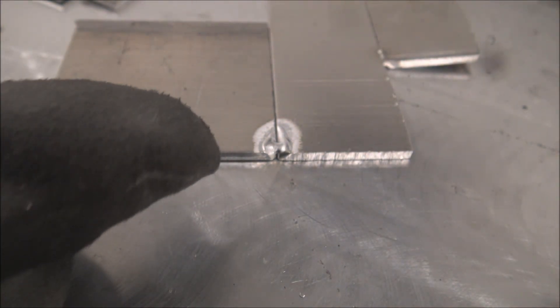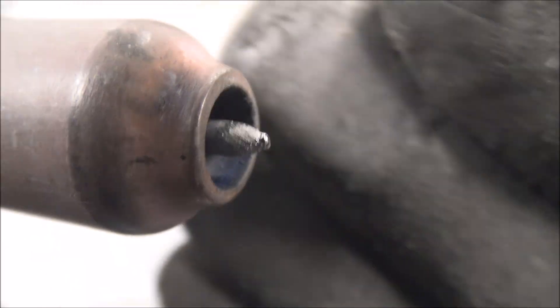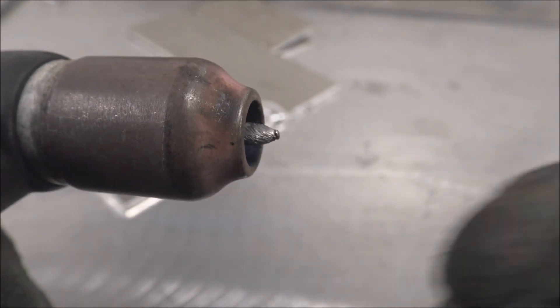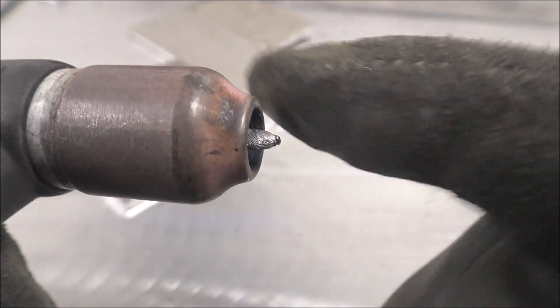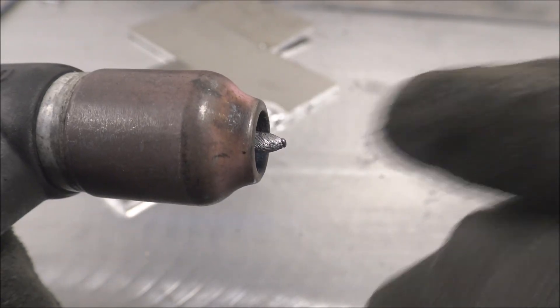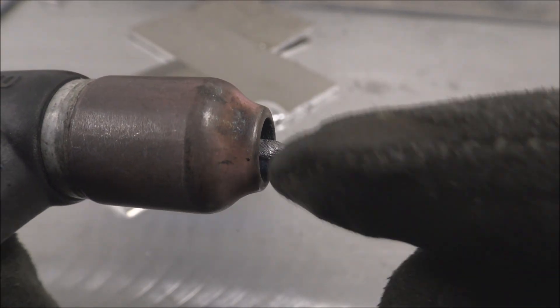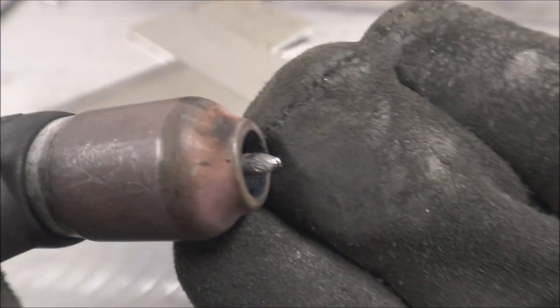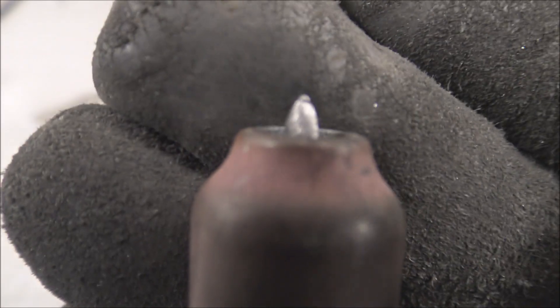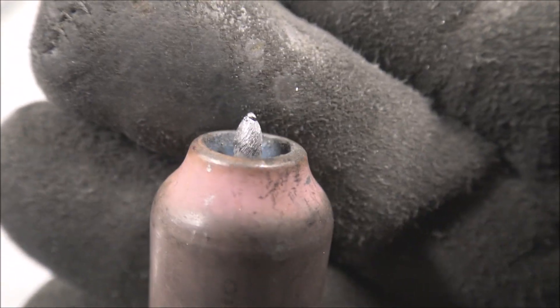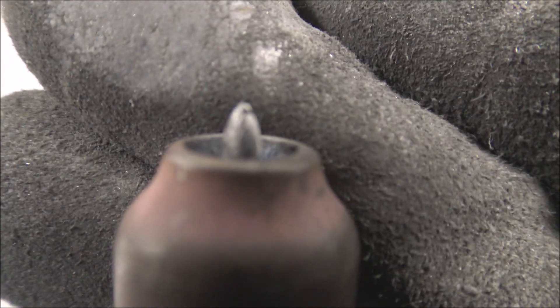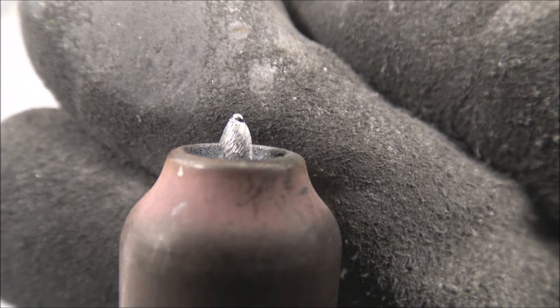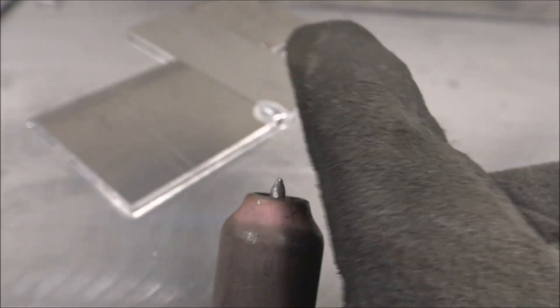I'm going to teach you how to do that a lot easier. First off, you've got to know how to shape your tungsten. At the bare minimum, no matter how you shape it (I teach you exactly how I do it on my website), you have to have concentricity. Looking at it from any angle, it's got to look the same with a line of symmetry right down the middle. See how that nasty ball is hanging off to one side? That shoots your arc off and it wanders around. The swirling from grinding at low amperages will make your arc wander and not stabilize.